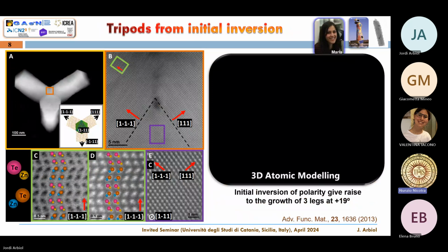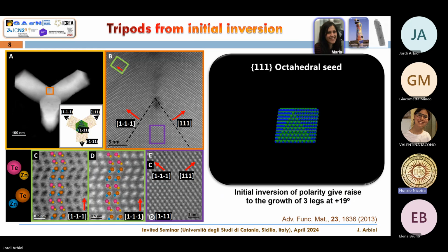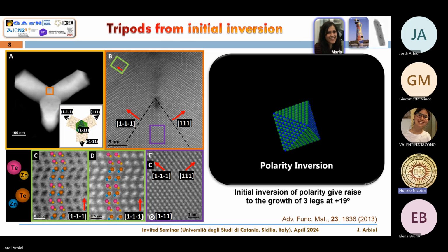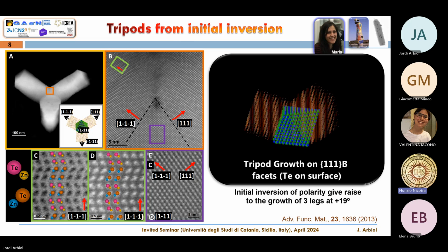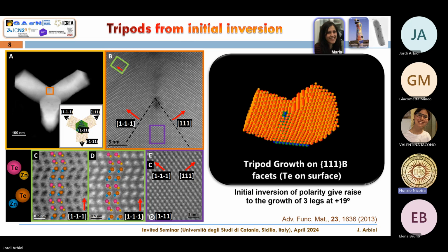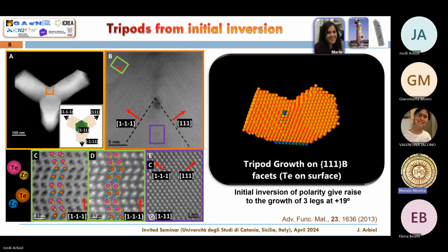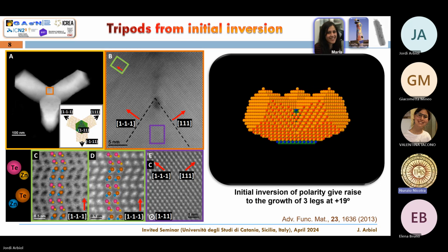So imagine that your first nucleation seed, if the video starts, is not terminated in the anion, but we reverse the polarity. Pretty slow this, it should be a little bit faster. But imagine that the blue one on top is the cation. So what we will have is 3 other available facets, and then the branches will grow along the anion, creating this really nice tripod that you can see here. So this is the structure of the tripod.